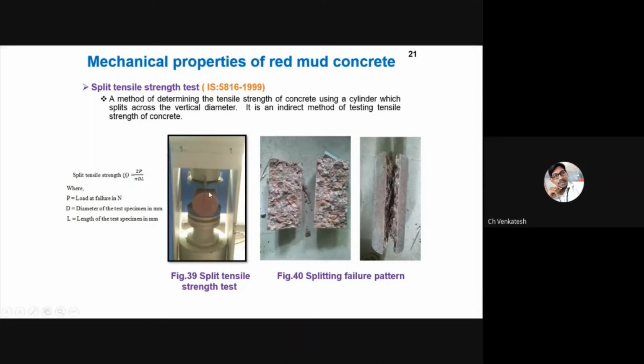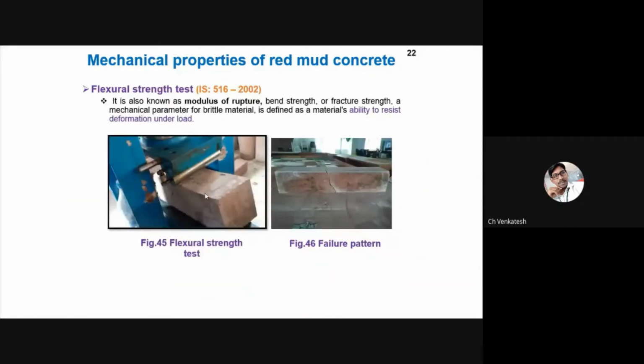You can see here in the compressive testing machine, the load is initially applied on a steel rod, and that steel rod is resting on the concrete specimen. So the rod contact area becomes critical, and there is a chance of developing more critical stresses at that point. That's why the concrete sample splits. Similarly, we also performed the flexural strength test to know the deformation under loading. These images show the flexural failure.